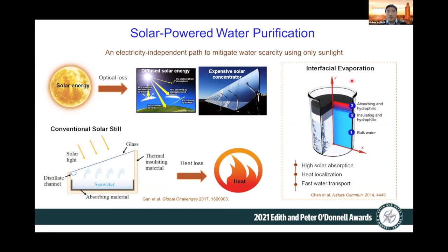And interfacial evaporation later became a very effective design. This is where you can utilize nanostructured materials to have localized evaporation at the surface. The three key design requirements are high solar absorption, very high heat localization at the interface, and plenty of water transport from the bulk to the interface. So you can minimize the energy loss during the process.